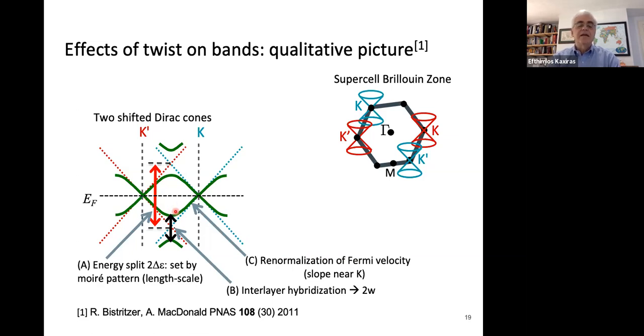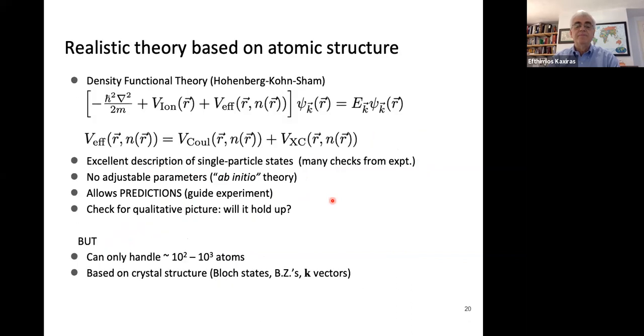And you can imagine that if you arrange these two different energy scales in just the right way, you might make these bands associated with the twisted bilayer very flat. And in this case, very interesting effects happen. So here's the density of states associated with the new bands. And for comparison, this would be schematically the density of states of graphene. And by creating these new bands, you make a density of states which is much higher near the Fermi level. And in the limit, when these bands are very, very flat, the density of states will become infinite.